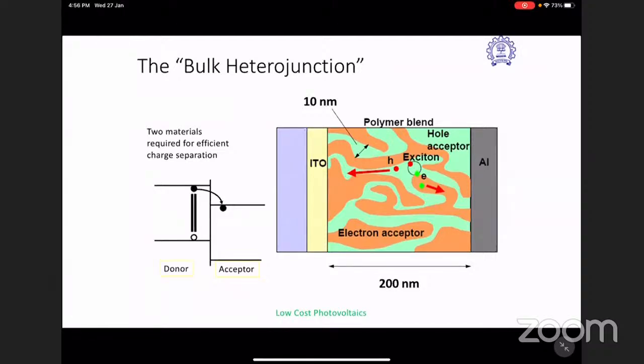The way you make the PN junction in silicon or gallium arsenide, you just make a bilayer, because exciton or charge carrier diffusion lengths are much larger than the thickness of those layers. But being very poor in charge transport, we make the intermixing in the range of 10 nanometers. So the exciton can diffuse to this interface and generate the charges. Okay.